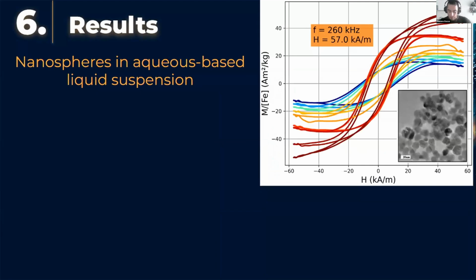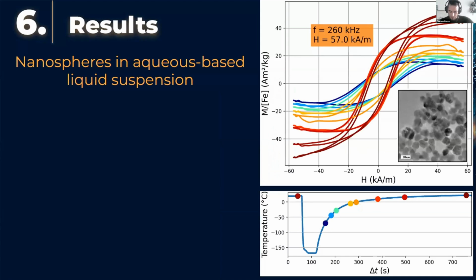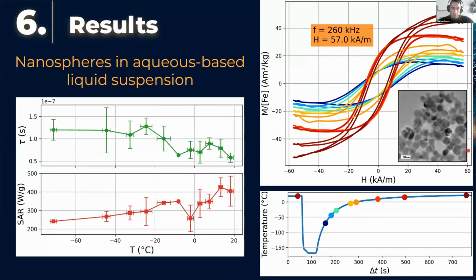Additionally, we conducted measurements of the radiofrequency cycles of citrate acid-covered magnetite nanospheres suspended in an aqueous-based solution. These measurements were taken during the process of thawing the carrier medium from cryogenic temperatures to room temperature. So we can show here the relaxation time and the specific absorption rate for the temperatures. And we can see that the biggest differences in the cycles occur here in the solid-liquid transition zone.